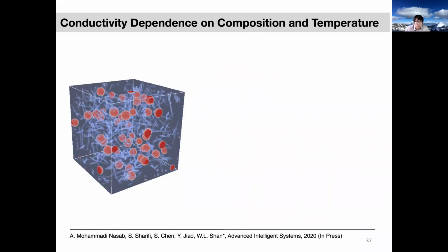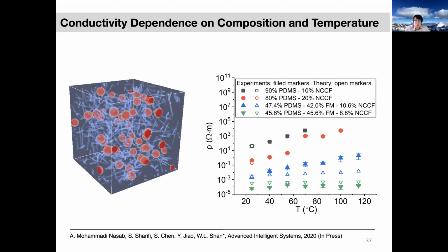We also used effective medium theory modeling. Actually, this was done by Professor Yang Jiao to estimate the electrical conductivity of the composite. As you can see, in this plot we have both experiments and theory. The experiments are filled markers and theory are open markers here. You can see that for the 3-component composite, it's very interesting that this conductive one doesn't change with temperature. Its electroconductivity doesn't change with temperature. We don't exactly know why this is the case. The simulation doesn't consider temperature dependence because of the lack of data for the nickel-coated carbon fiber. So for both cases, you don't have much change here.